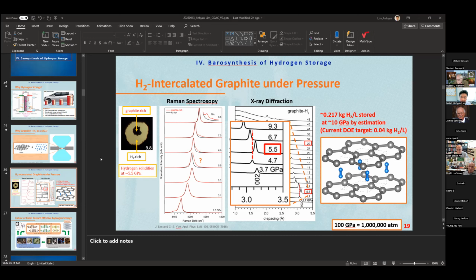Our Raman spectroscopy shows that the hydrogen goes into the graphite, with distinct peaks different from the pure hydrogen. And at the same pressure, we see in the diffraction pattern that the C-axis increases. I think it's strong. Yeah, but that could also be given by an external stress, not necessarily by an intake. But when hydrogen freezes, it's actually a very, very weak solid, and you can measure that stress.